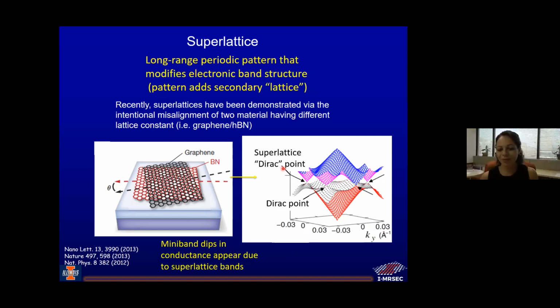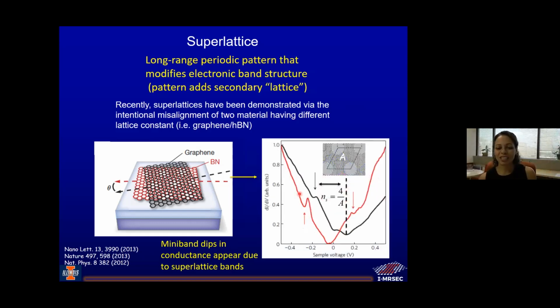It looks like that. But what it really means is that when you measure transport, and this is data for the graphene boron nitride device, you get the Dirac point for graphene, and then you get an additional superlattice dip. And it shows up kind of like a peak and then a dip here due to the superlattice, and that shows you that you have a superlattice across your device, and you're dealing with two different lattices. Okay, so we want to see how this shows up in our strain device.